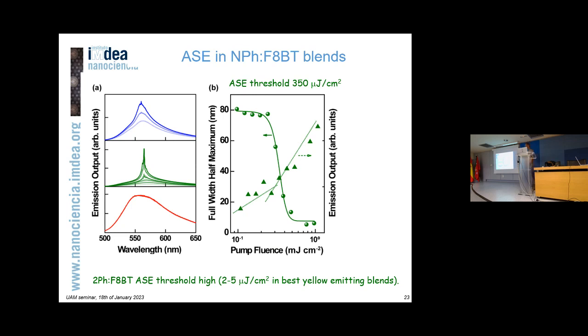And then we took these polymers, blended them with F8BT once more, and tried to understand if they have optical gain. This time we did what we call amplified spontaneous emission measurements. The idea is that, rather than exciting the film with a circular spot like in a conventional photoluminescence experiment, we excite it with a narrow stripe, and we collect the emission wave-guided at the edge.